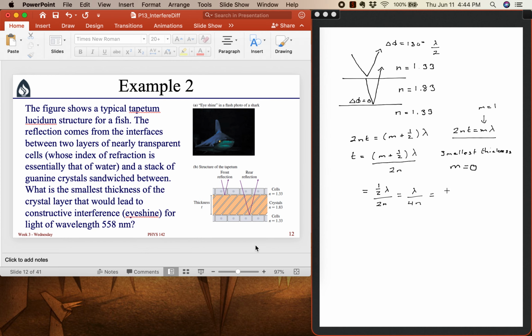So if we put in some numbers, lambda, the wavelength of light, is 558 nanometers. And then we divide that by 4 times the index of refraction of the film, which is 1.83. So for that, we get a thickness of the crystal layer of about 76.2 nanometers. So that's the thickness of the layer at the back of the fish's eye.